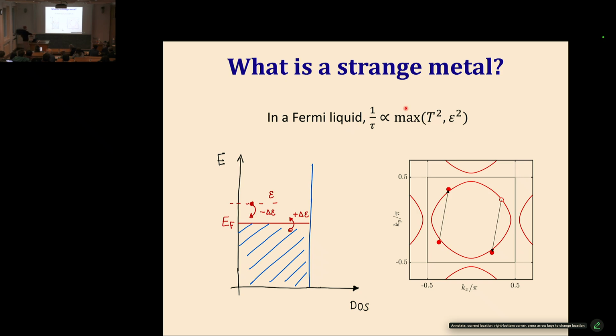If you look at the density of states of quasi-particle excitations close to the Fermi surface, that's a constant. There's a constant density of states. The value of that density of states depends on the shape of the Fermi surface and the effective mass and so on. But there's some constant. And now if we start from a single quasi-particle, some energy epsilon above the Fermi surface, and ask about the collision rate or the scattering rate of that electron with all the other electrons, a simple phase space argument would give you immediately that that actually goes like the energy squared.